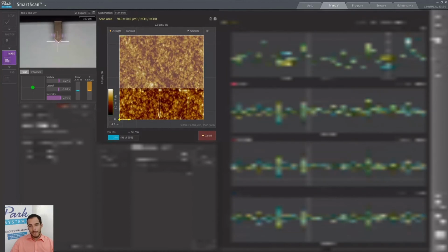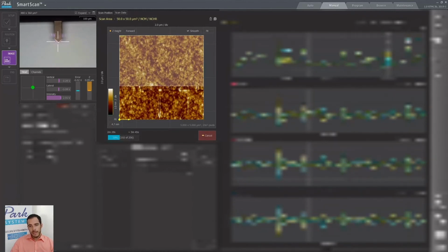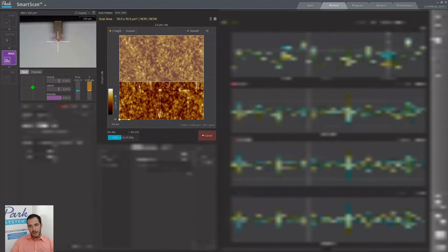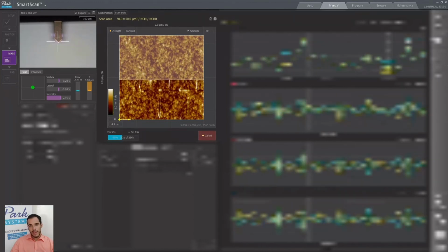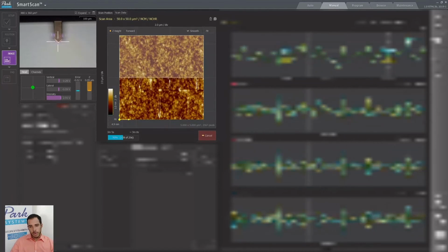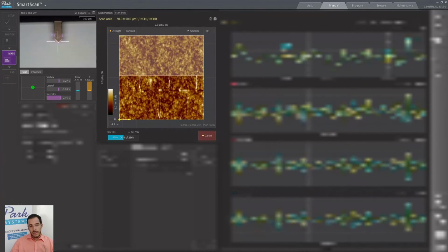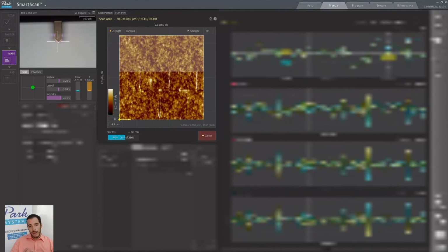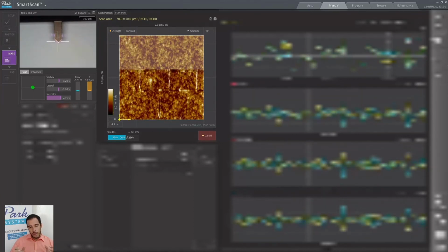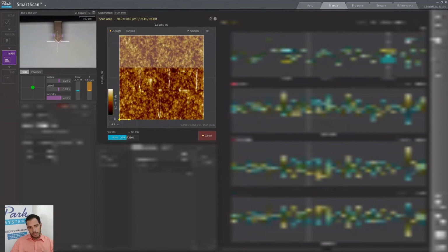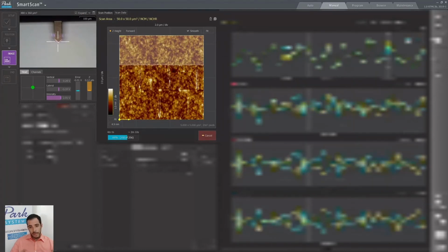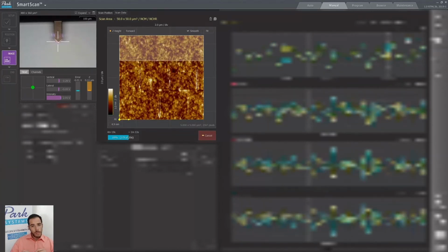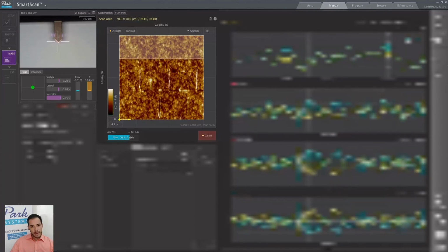If we look at the topography channel and the signal, we insert the cursors, but they are not landing exactly on the grooves we created. But we can actually see the grooves that were created, because we can also see an increase in the topography. Whenever we created a groove, the film around it got accumulated and created a bigger difference in topography around these grooves. And we can clearly see the squares, it has the same phenomenon as the lines.